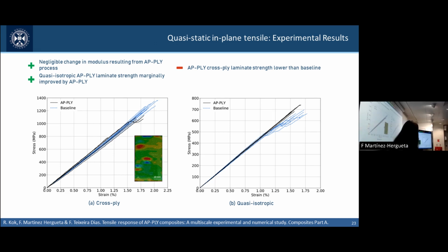But we do not see the same when we evaluate the quasi-isotropic laminate, but that has to be also related to the failure mechanism. So in these quasi-isotropic laminates, the first failure that occurs is not fiber failure, it is matrix cracking. At that point, what we will have in a conventional laminate is matrix cracking of the layers oriented at 90 and at 45 degrees, and that will originate this softening that we observe. That did not occur in the AP-PLY laminate. The AP-PLY laminate was linear elastic until final failure.